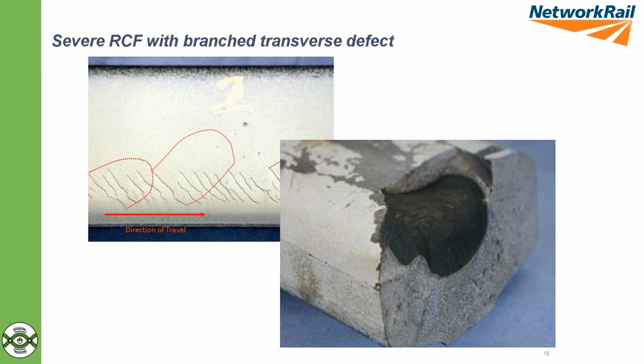RCF, it's not gone away, and in general, looking at data, it is still increasing. The volumes of severe RCF are still increasing, not particularly quickly, but they are slowly creeping up. This is an example of a rail. This is surface cracking you can see in the top left picture, highlighted with magnetic particle testing. The red line indicates there is the crack growth under the surface, and this is the sample actually broken open at the point of position 2.